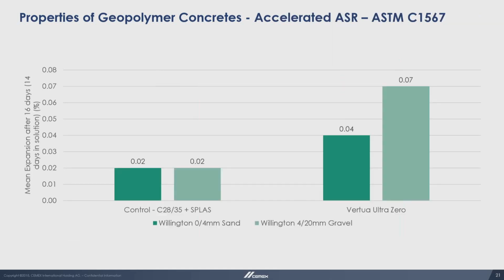And the one area that is often asked is around, well, these are alkali activated materials. Are they resistant to ASR? And on the testing that we've done, we've seen that they are slightly higher expansion than you would get with a traditional blended cement. So, this is compared against a fly ash based cement. And it's slightly higher, but lower than the limit. The limit is 0.1 for deleterious ASR, and so it's below the limit. So something to be aware of, but generally, and certainly a lot of the literature would indicate that they're not susceptible to alkali silica reaction in the way you may expect.